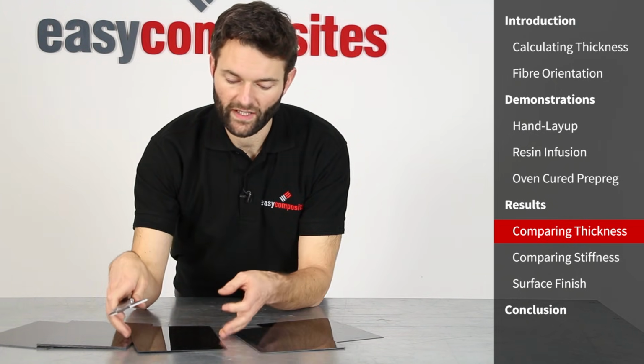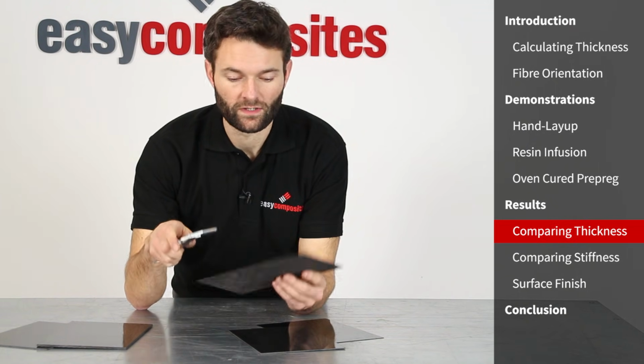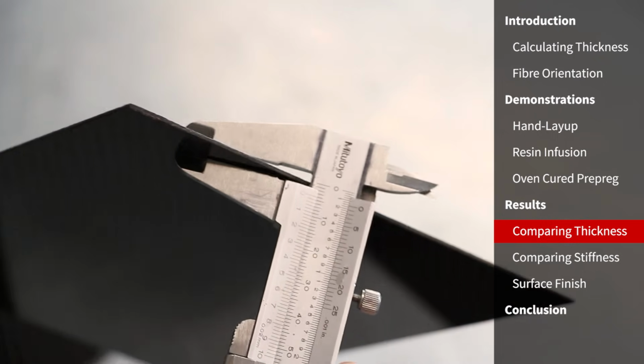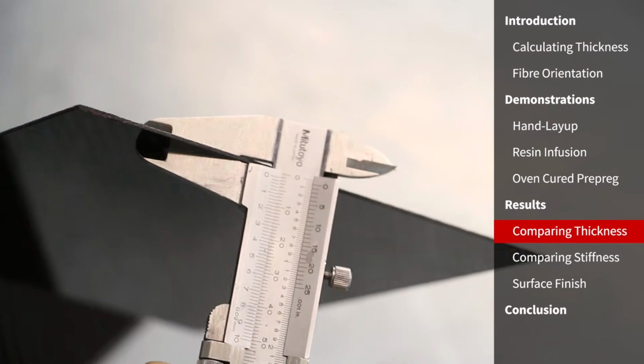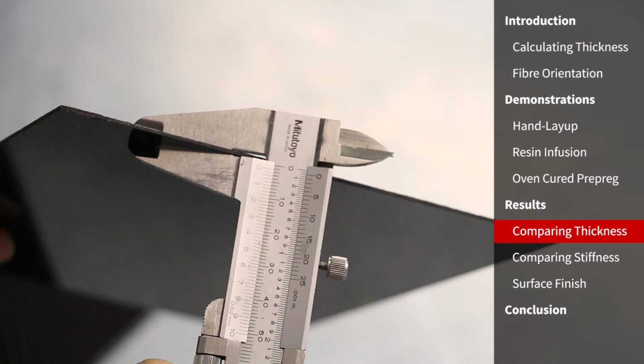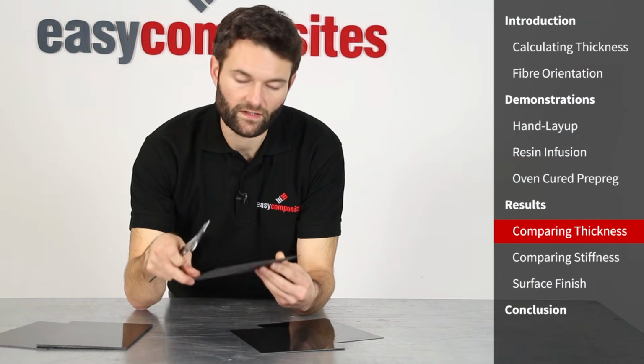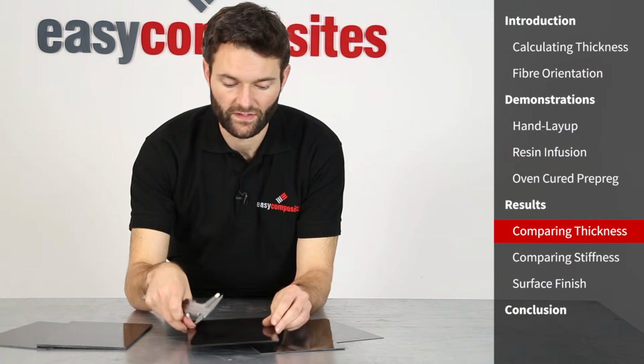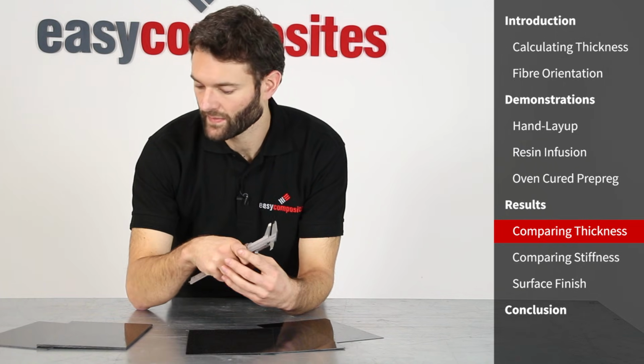We did the exact same layup with the resin infusion, and if we have a look at the thickness of that, then that's much closer to the thickness that we were anticipating. So this is coming up at 1.3, and we were expecting around about 1.2. So that's pretty close to the consolidated thickness that we'd expected.